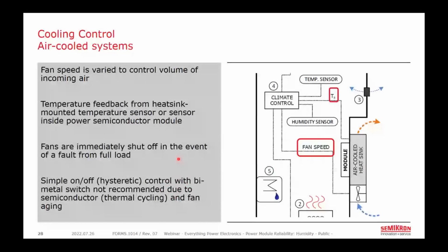So one of the methods we'll talk about here is cooling control. In an electrical enclosure with an air-cooled power converter, we can manage the operating point by monitoring the heat sink temperature here, or even better, the temperature inside the module, and controlling our fan speed. And doing so lets us avoid the condition we talked about in the last section, where a power module is operating at a really high load in a humid environment, and you suddenly shut off the system, and the heat sink is continuing to be cooled.